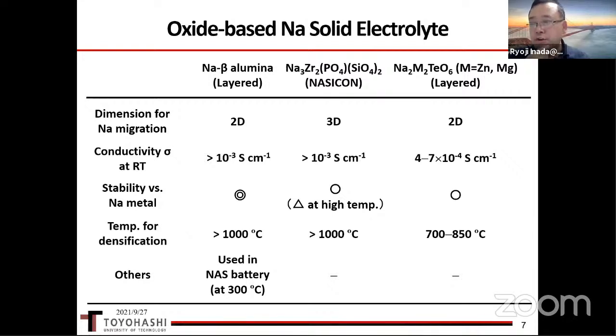The history of the oxide-based sodium solid electrolyte is very old, as you know. Even in the 1970s, the two famous materials, sodium beta alumina and NASICON, were discovered, and their room temperature conductivity attained above 1 millisiemens per centimeter. These two materials also have a wide electrochemical potential window and are stable against sodium metal. And sodium beta alumina is practically used as the electrolyte in the NAS battery developed in Japan, which operates at 300 degrees C, composed of a melted sulfur cathode and a sodium anode.